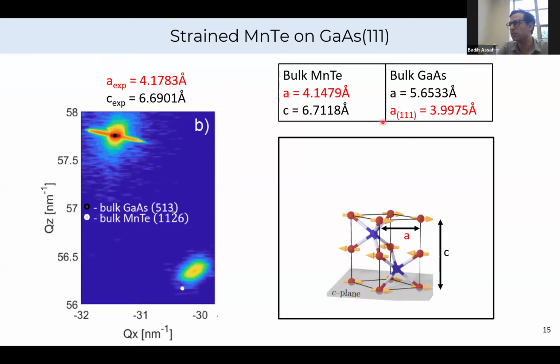This was a bit surprising because the A lattice parameter of gallium arsenide (111) is actually smaller than bulk. So that tells us that the dominant strain source is actually not lattice strain. What it turned out to be is that this strain, which stretches out MnTe in the plane, is simply related to the fact that gallium arsenide has a very low thermal expansion coefficient. So when you cool down your sample from the growth temperature to room temperature, your substrate shrinks at a rate that's actually much slower than your layer, leaving your layer under tensile strain. It actually expands the in-plane lattice parameter.